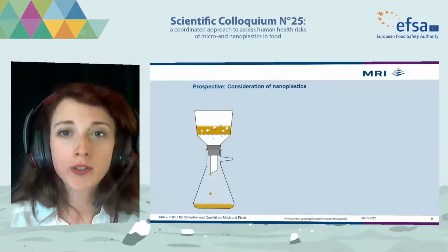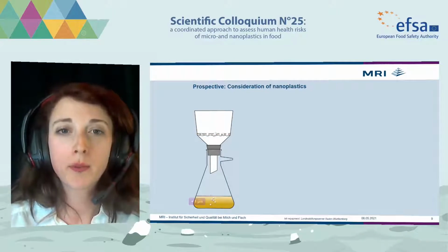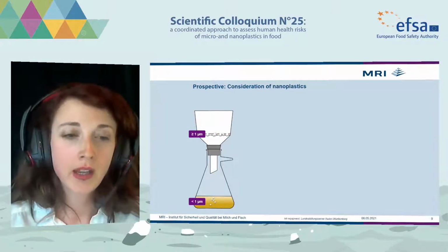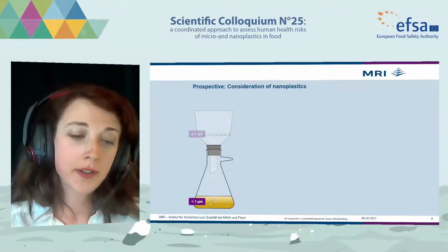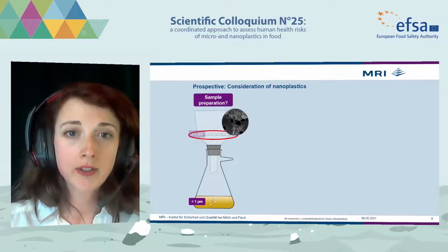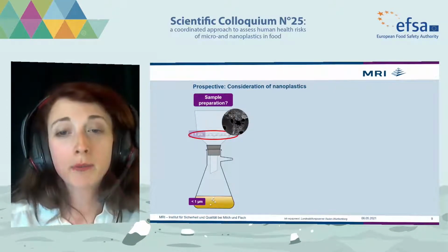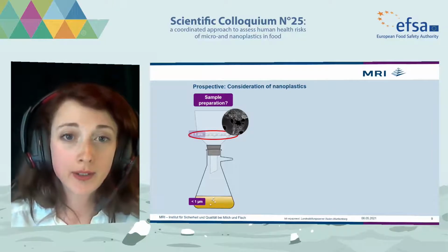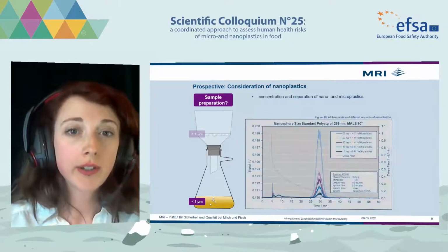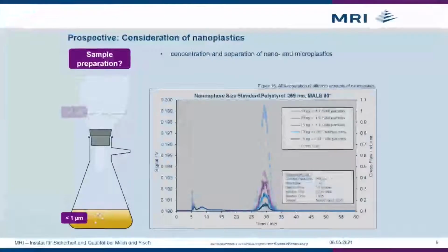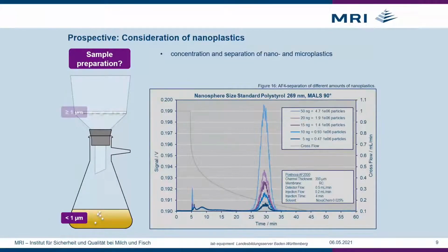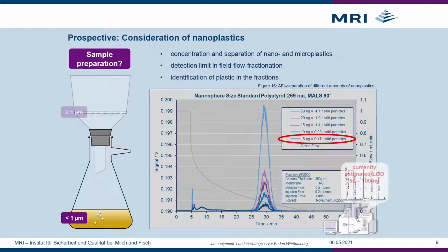Our first assumption was that nanoparticles will be separated from microparticles during filtration. However, our preliminary filtration tests showed that there is still a research need regarding other sample preparation methods for the isolation of nanoplastics. We also conducted first tests regarding concentration and separation of nanoplastics with asymmetric flow field flow fractionation. Regarding the detection limits of AF4 and pyrolysis GCMS for consecutive identification, however, these still need further improvement.